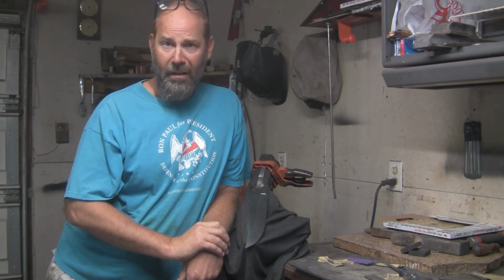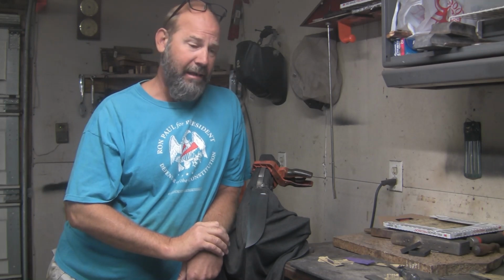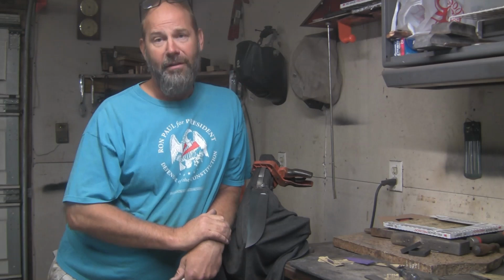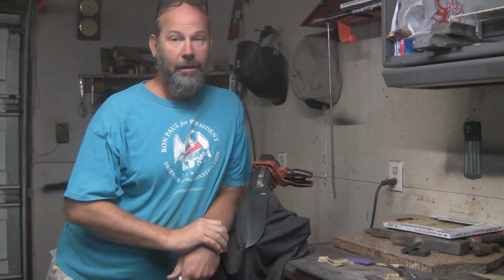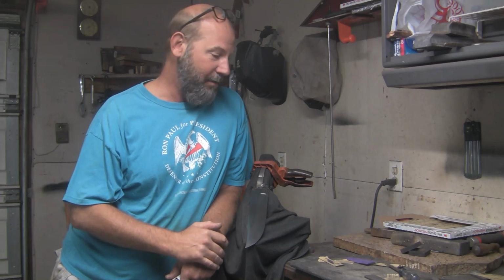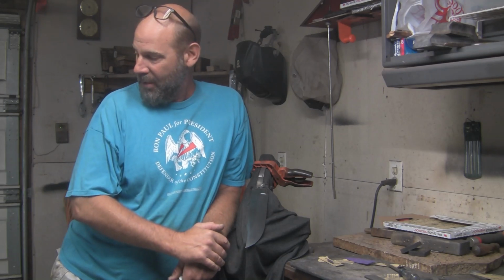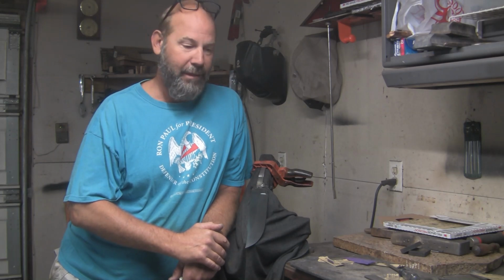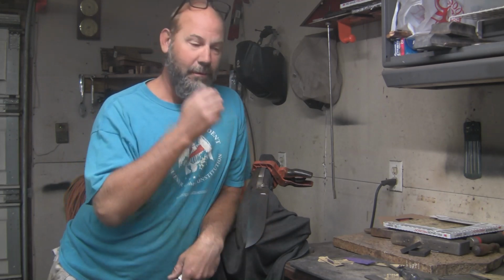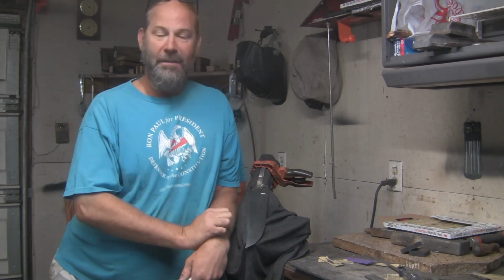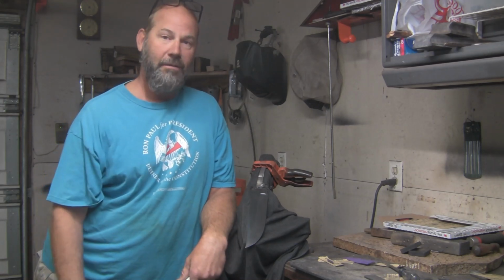I'm just afraid with a full water harden it's going to crack, and I would rather try this first than not harden, then normalize and have to do it all over again, and then just go straight to water and crack it. So this is what turns a flat pointy piece of metal into a knife. This is kind of make or break for the blade. Straight water hardening worries me a little bit, but that's why I'm going to do a two-stage quench. So in the water, in the oil. Hopefully it works out. Hopefully I get a really nice hamon, and hopefully we got something we can show off and be proud of. So stay tuned, and we're going to get on to the heat treat.